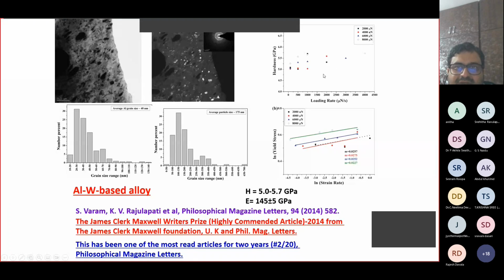And hardness is really high, more than 5 gigapascal in an aluminum-based system. And even the modulus is 145. That's really good. And for this paper, we also got an international prize from the James Clerk Maxwell Foundation, which is based in the UK. And this article we published in 2014, and even after 8 years, it is one of the top 3 articles. It was 2 sometime back, but I think now it's at 3. Top 3 under most read articles in Philosophical Magazine Letters, and I'm very happy to inform you all of that.